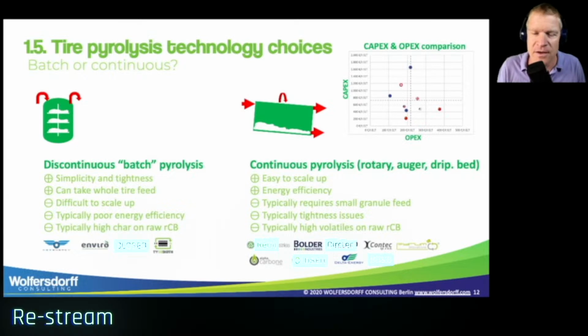You might have heard of the fire at Black Bear Carbon. That was hydrocarbon gas getting out and meeting hot surfaces and then causing the fire. And this is not the only technology and the only company that had this challenge. Typically also, because in the continuous kiln we have a set temperature and a limited residence time until the raw recovered carbon black leaves the reactor, continuous pyrolysis tends to have high volatiles on the raw recovered carbon black. That could be, for example, 3%.